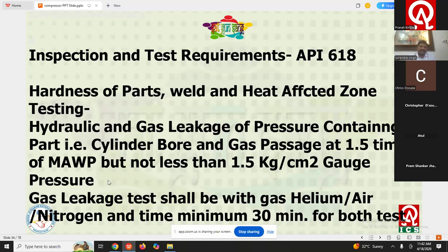Again, after the hydraulic test, a gas leakage test is also required in API 618. Gas leakage is just a pneumatic test, but the media is given as helium, air or nitrogen based on what fluid will be used during service. If it is a petroleum product, then we have to use helium as the media for the gas leakage test. If the compressor is used in service for air or other non-hazardous gas, then air or nitrogen can be used as the gas media for testing. The code also gives a minimum time of 30 minutes for this pressure to be held for the gas leakage test.